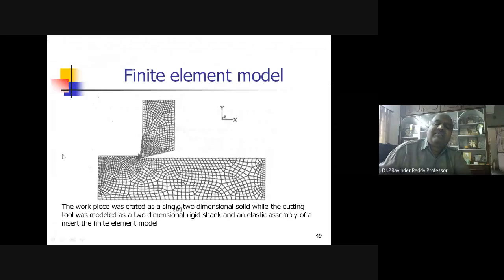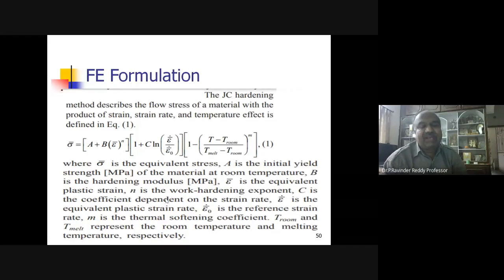Conventionally when you see a small chip, this is the work, then the tool, then you have the chip. If you see here, the mesh density is going to vary, because here there is a shear zone. We need to have a larger number of elements, and on this side of cutting there is a contact between the tool and work. You should have more elements, and you have a contact between tool and chip, so you should have more elements. For this we have removed the rest, and we are trying to have more elements, because this is our important zone, and this other zone is not at all a concern. Only for the sake of some shape we have kept it, but otherwise our total interest is only this part. So it is a localized mesh, we need to have a very refined grid size.